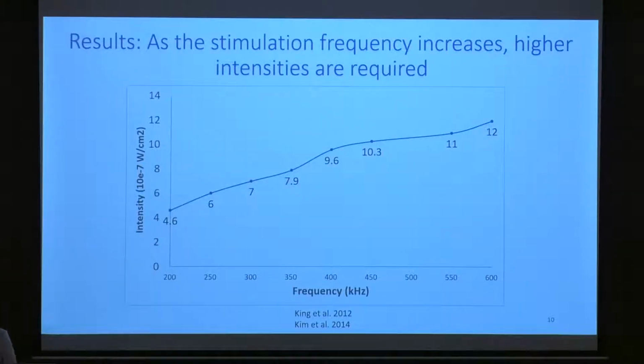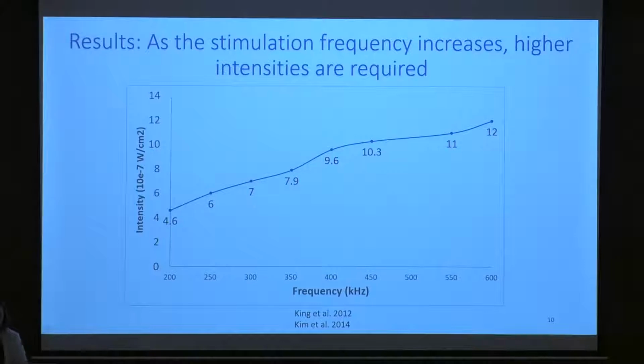And this is actually compatible with some work in literature. We also noticed that at lower frequency, we require much lower intensities to cause variations in the action potential in the Hodgkin and Huxley model. And this is probably due to the fact that with higher frequencies, when the wave travels into the tissue, it tends to undergo more diffraction. But this is a theory, and we're trying to vary more parameters to check this theory. When the wave diffracts more, this reduces the impact on a specific region.